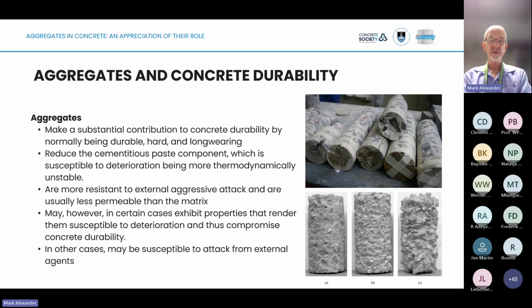Very briefly, I'll bring this thing to a close now. Of course, again, aggregates here, paste is not a durable material in effect. But when you put aggregates in concrete, you can produce a durable material because the aggregates are generally the most durable component of a concrete. They are not susceptible to leaching or to acid attack and so on and so forth. And here on the right, you can see sometimes we get internal lack of durability due to aggregates. Sometimes they can cause problems.